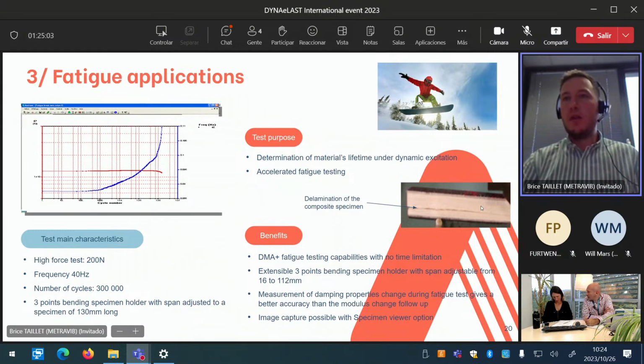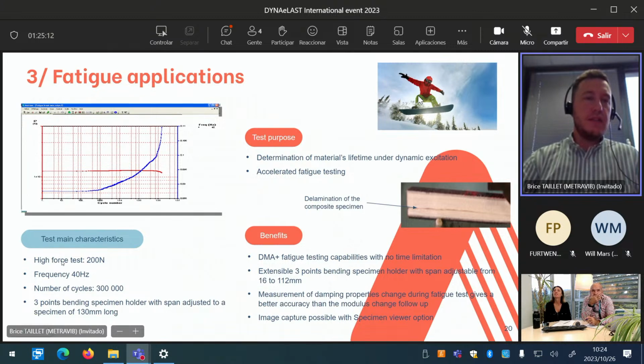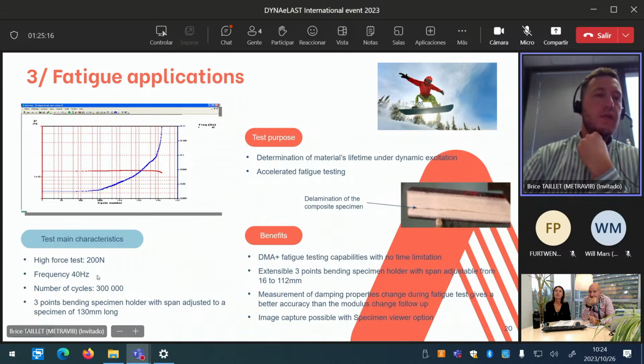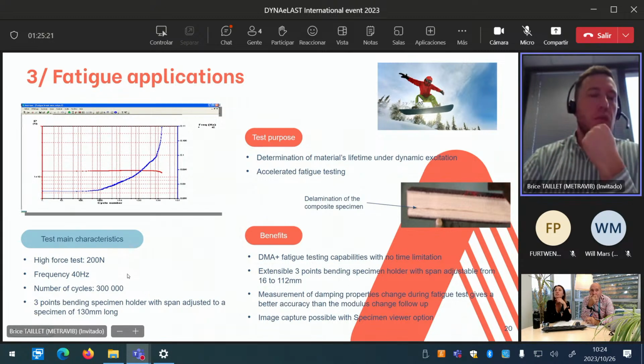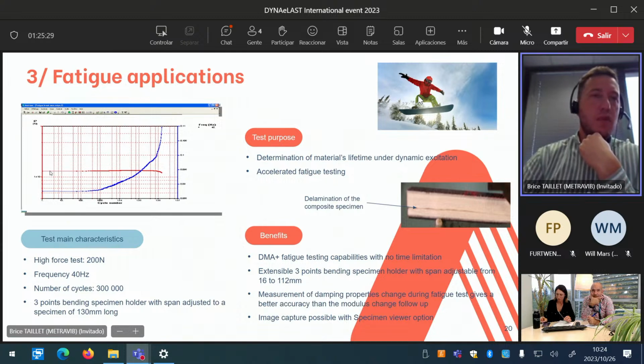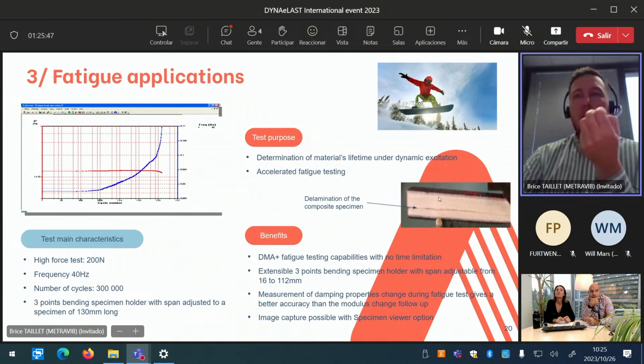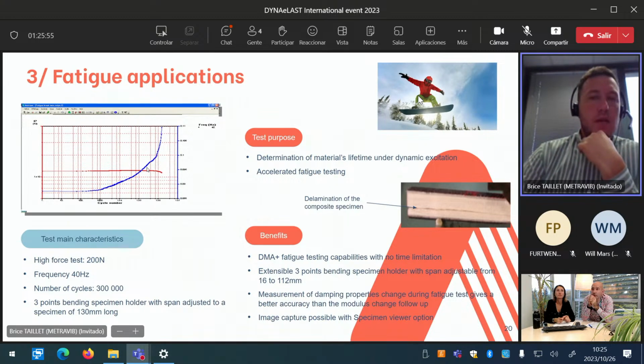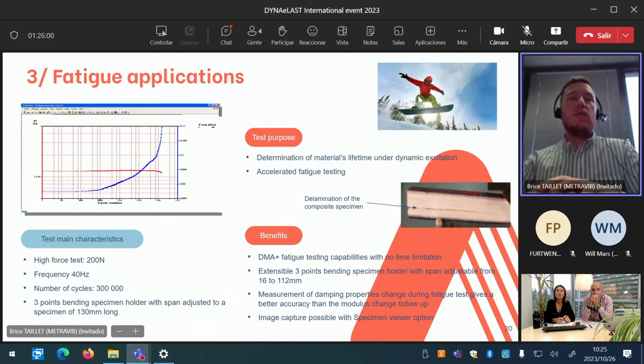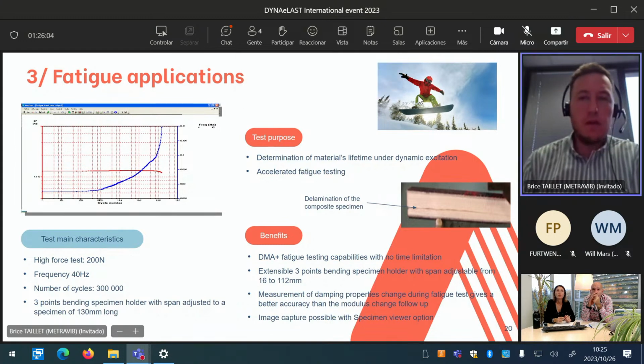I show the example of a snowboard in a 3-point bending mode, applying a high force test, plus or minus 200 Newton, with a frequency of 40 Hertz and 300,000 cycles. As you can see, if you are looking at the red curve, that is to say the evolution of E prime as a function of cycle number, we don't see anything interesting. But if we are looking at the blue curve, that is to say the evolution of tangent delta, you can see that above 100 cycles, something happened inside the material, and after a picture, we can see the beginning of the delamination of the composite sample. So DMA can provide some quite precise information regarding the failure mechanism for a testing specimen.